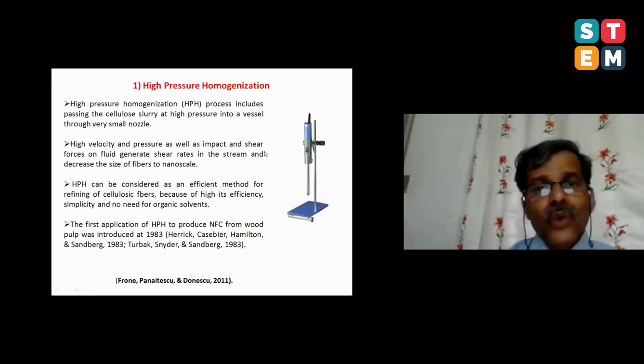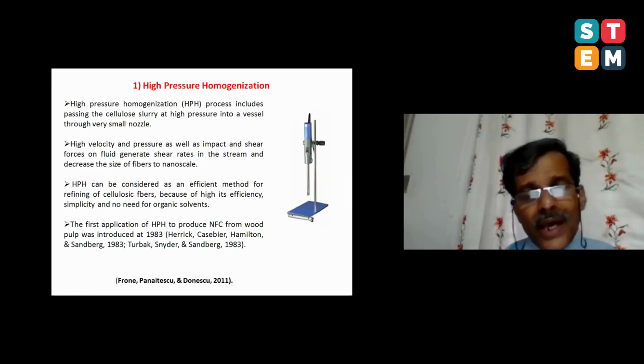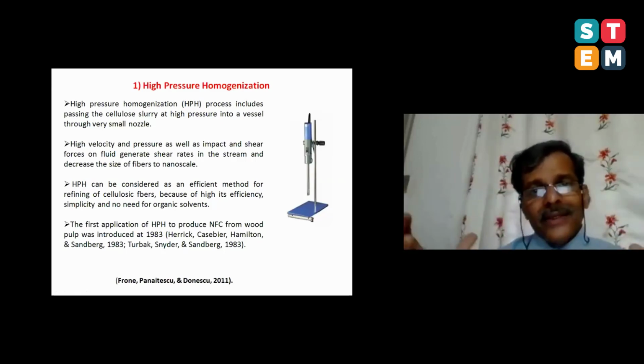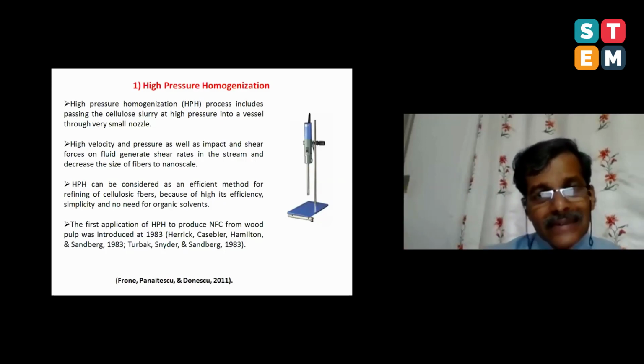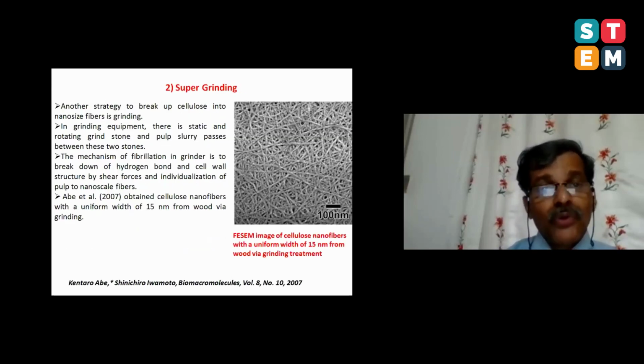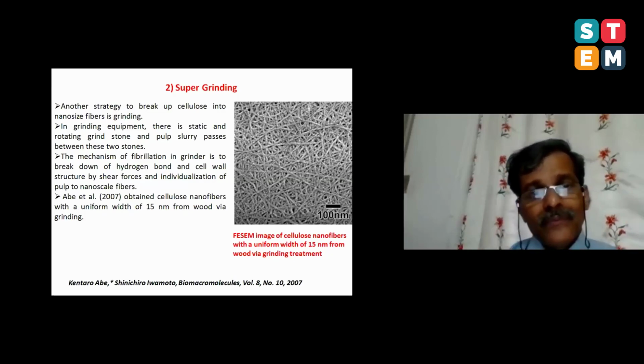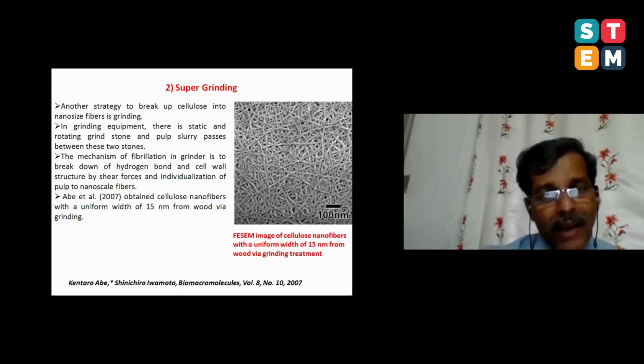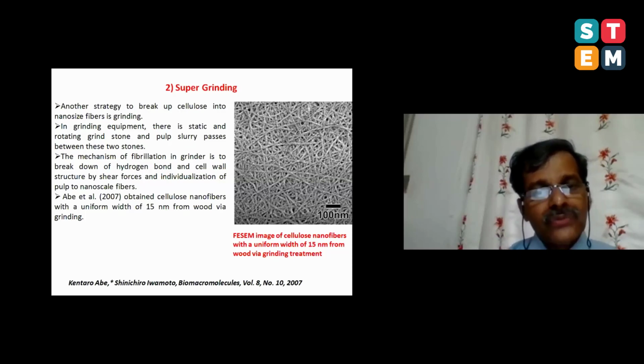High pressure homogenization: what we do is we pass a slurry, cellulose slurry, at high pressure into a vessel through a very small nozzle. When you do that, the material is subjected to very high impact and shear forces. As a result of this, you can get nanocellulose. The second process is super grinding. In super grinding, there is a static and a rotating grindstone, and by the shear forces, the macrocellulose can be transformed into nanocellulose. You can see some nice pictures of super ground agro waste.